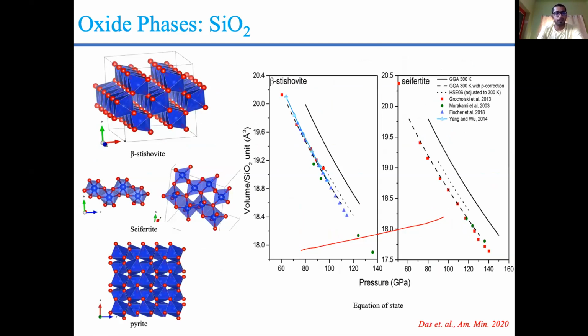I already told that GGA always overestimates the volume. So this thick black line is our equation of state, which is almost 12% higher than the experimental data. So we made a correction to this GGA result. That is nothing but a negative shift of pressure, and you can see it lies on the experimental value, this black dashed line.